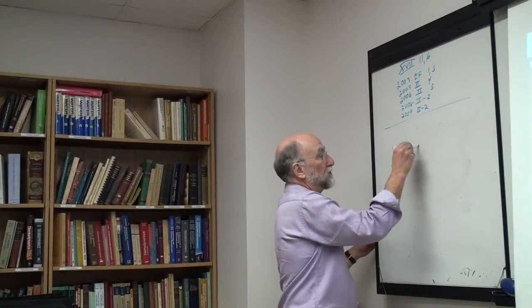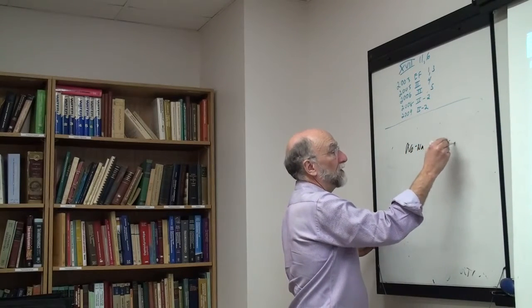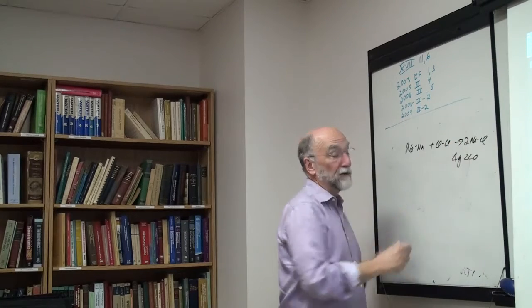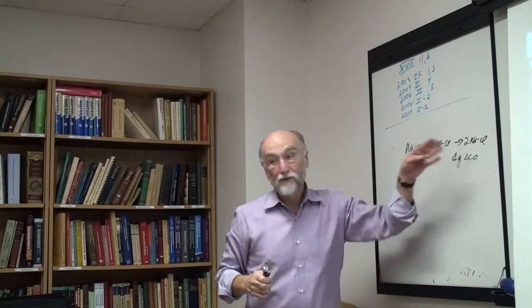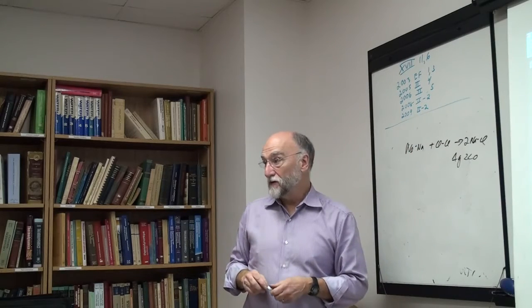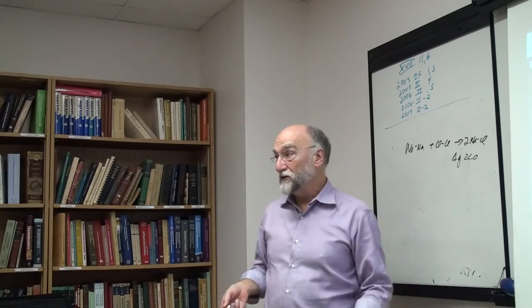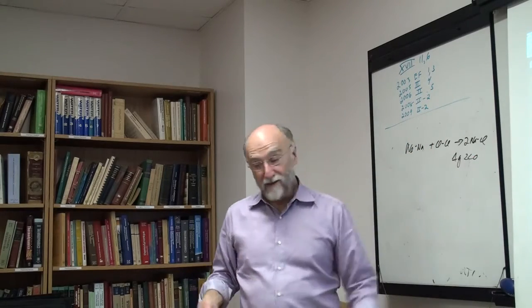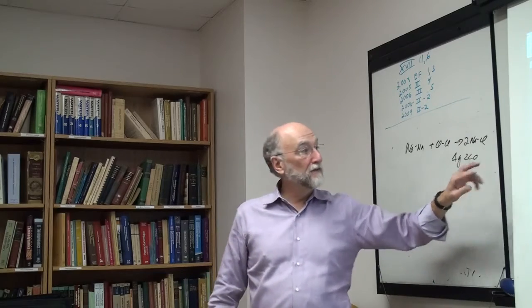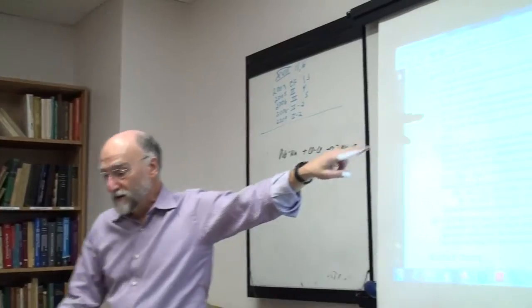But sodium-sodium bonds plus chlorine-chlorine bonds form two sodium-chlorine bonds. The delta G for this is extremely negative, so this is pushed almost entirely over to the right. And the same thing for the KCl. In that case, this is sort of the correct model that you should use. But you're going to see that in the limit, as this becomes infinitely negative, it reduces to this model, which is mathematically much simpler. But there are also certain limitations too.